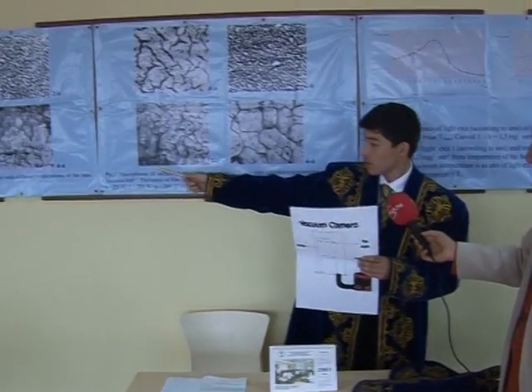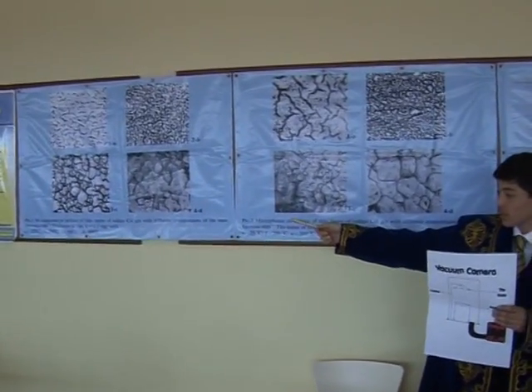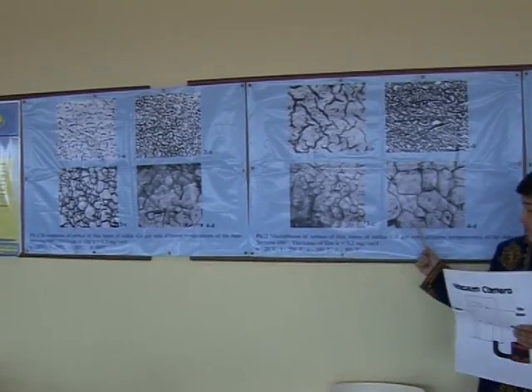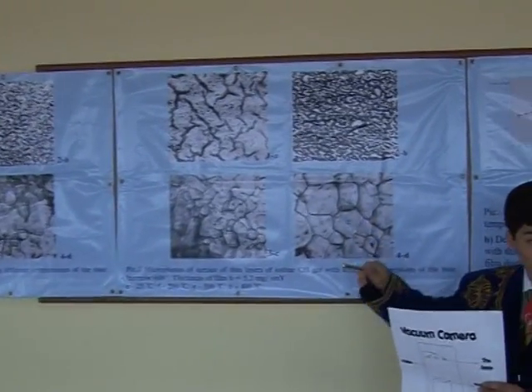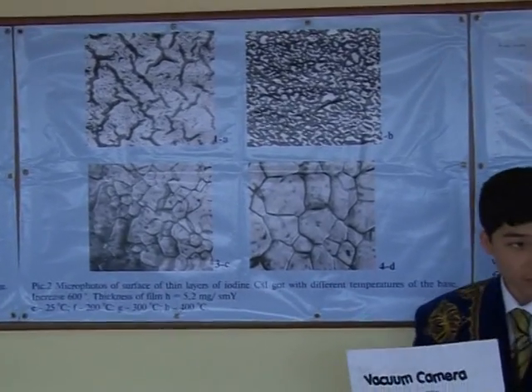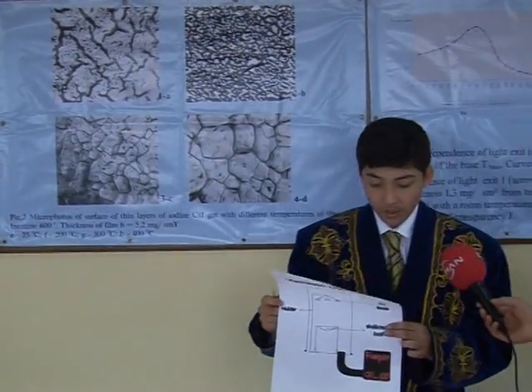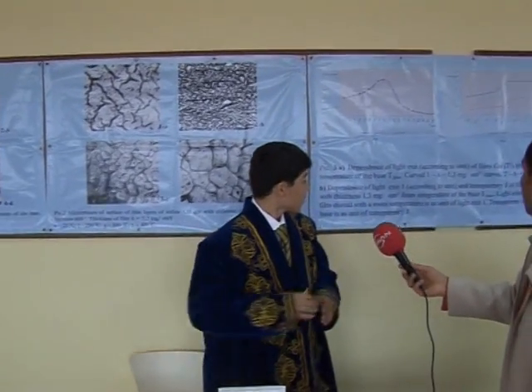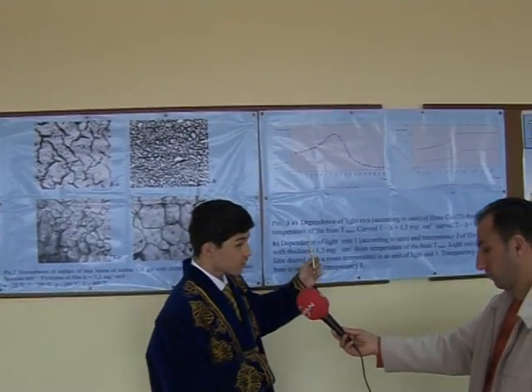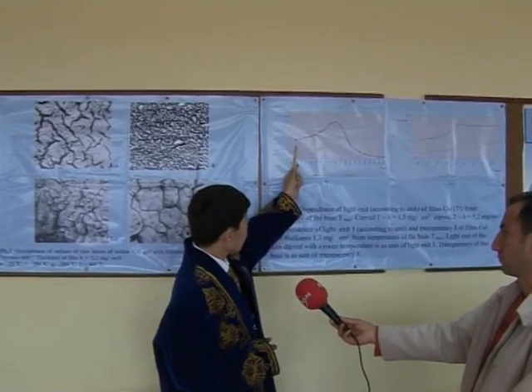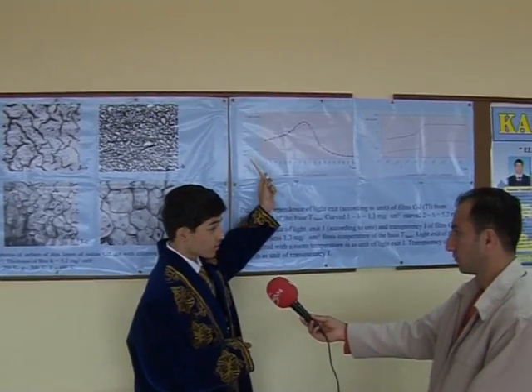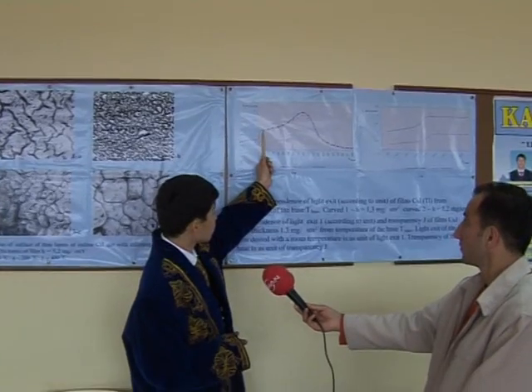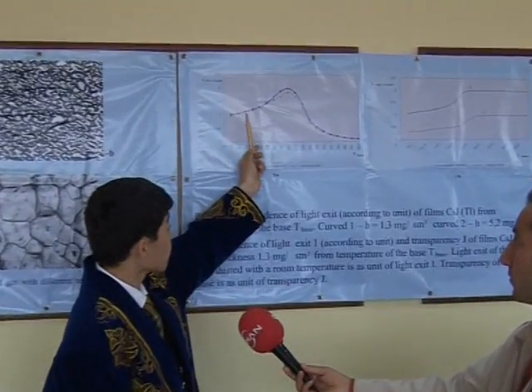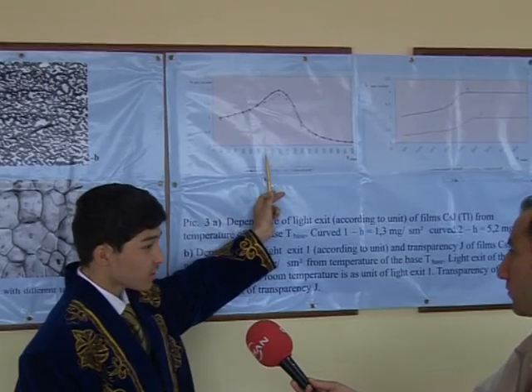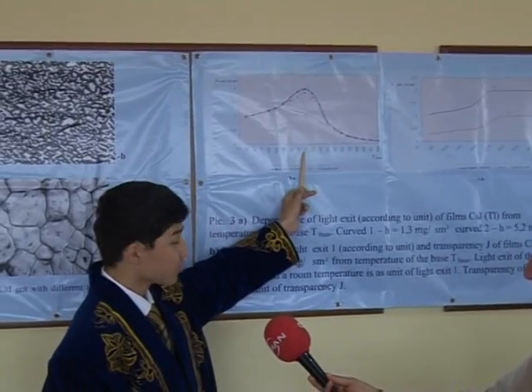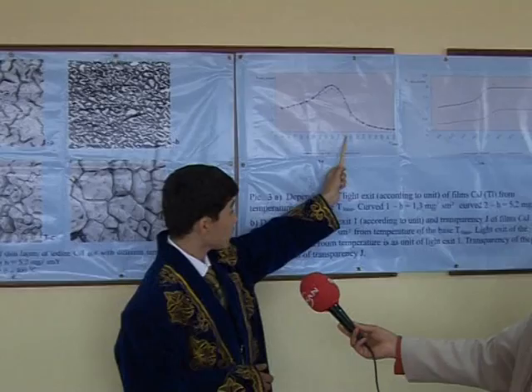In the first picture, the thickness of the film is 1.3 milligrams per square centimeter. In the second picture, the thickness of the film is 5.2 milligrams per square centimeter. And then, if we increase the temperature of the base, the light exit of the cesium iodide film will increase, reaching a maximum at 200 Celsius, and then it lowers quickly.